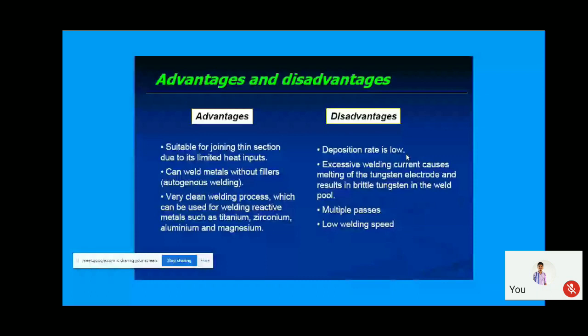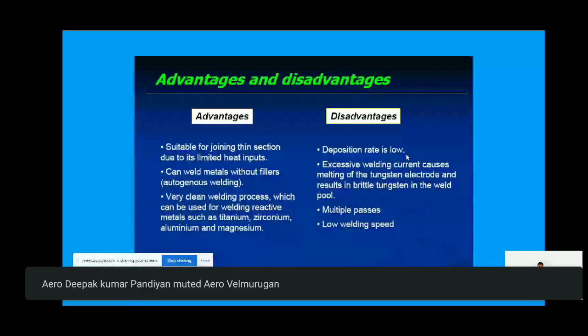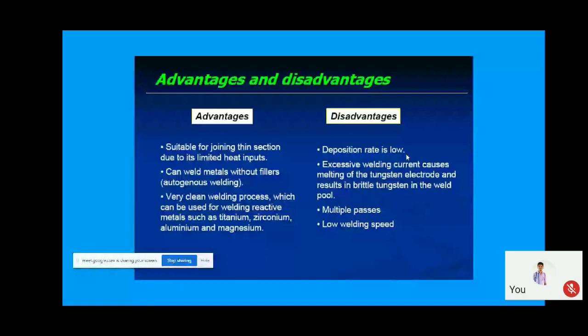So excessive welding current causes melting of the tungsten electrode and results in brittle tungsten in the weld pool. So you can see the weld process can be used for welding reactive material, even titanium, zirconium is possible over here, and multi-pass is possible and low welding speed. This is the disadvantage. And these are some of my own reference papers which I worked closely on with the GTA and PCGTA with the different grades of superalloys. And another process called the ATIG welding process.